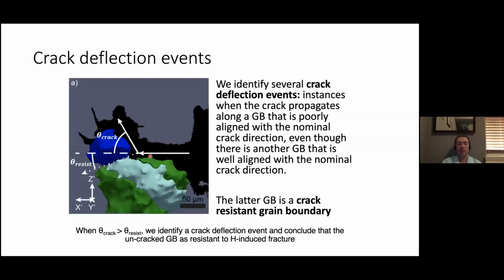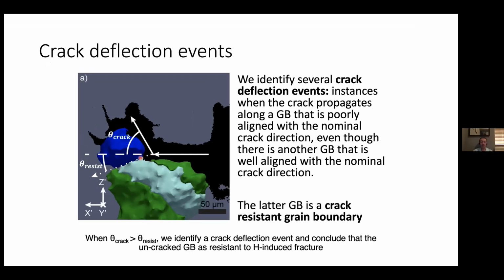What we found when we did this study is that if you look at how the crack is progressing through the material, in this particular image, the crack is coming from the right and moving to the left. There are a number of crack deflection events where the crack is propagating along a grain boundary. It encounters another grain boundary like this one, which seems to be very favorably oriented for the crack to continue propagating along it. But instead, what the crack does is it goes around the grain, it takes a detour, right? Circumventing this grain boundary, avoiding it, in other words. So these crack deflection events signal to us that this particular boundary, the one that the crack is avoiding, is especially strong.